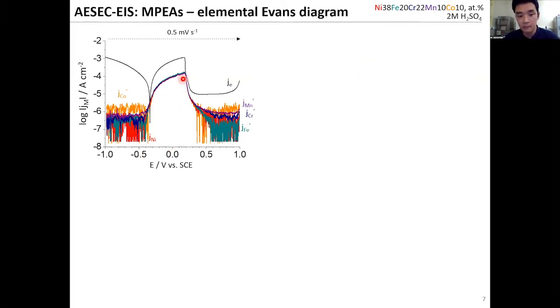And we can have the information of elements, so we have how much each contributes to the total current density. When we sum up, it doesn't really reach this black curve, which is the total current density. That means there's probably certain oxide formation, or oxidation charge that did not contribute to the total current density.